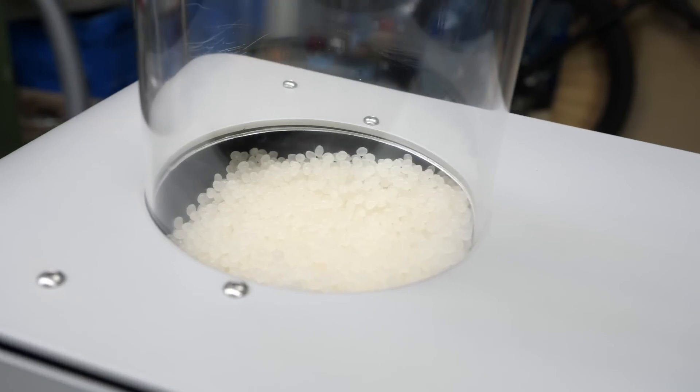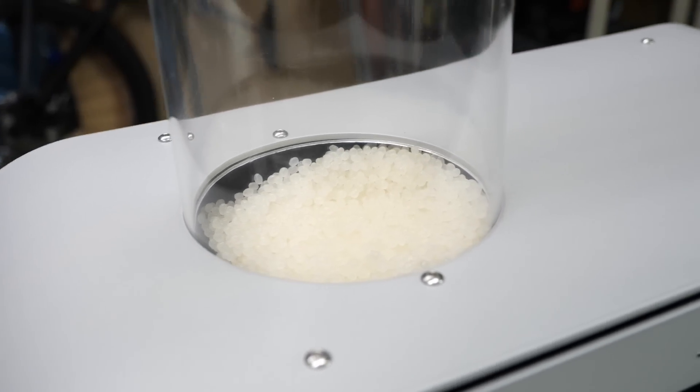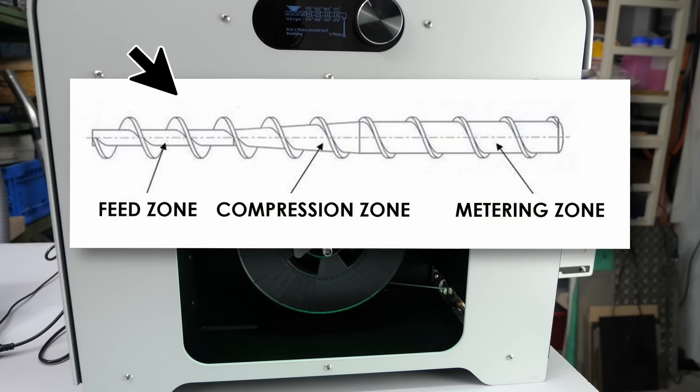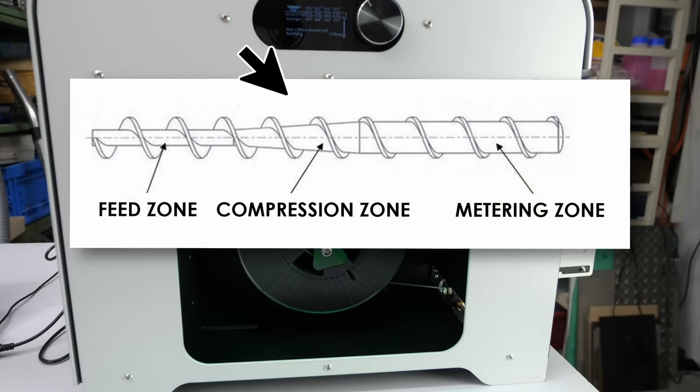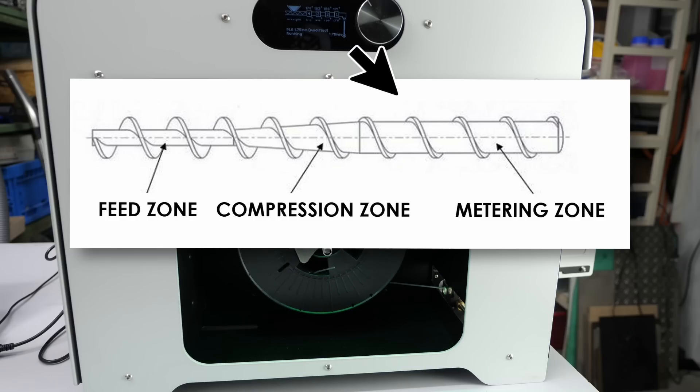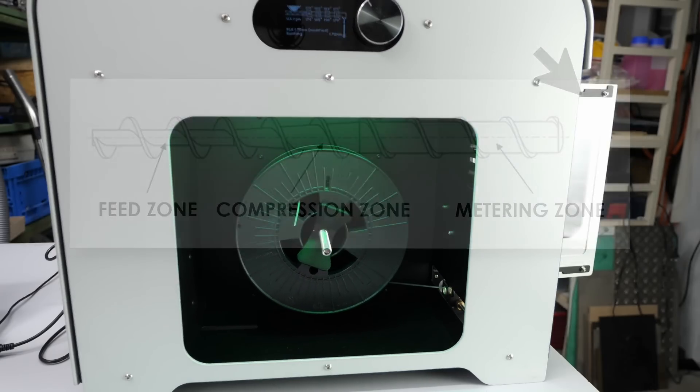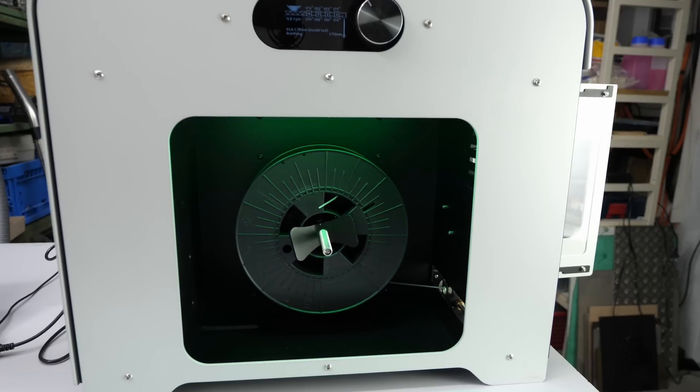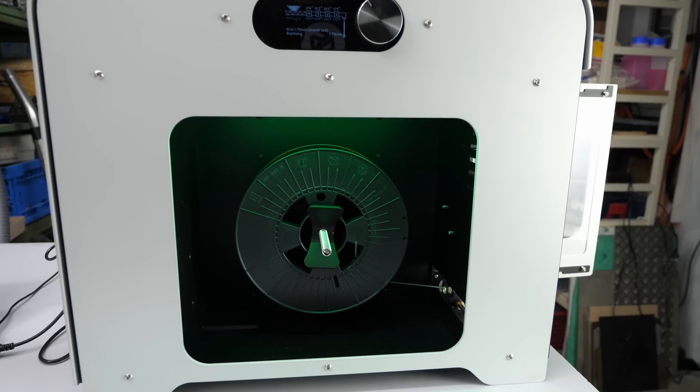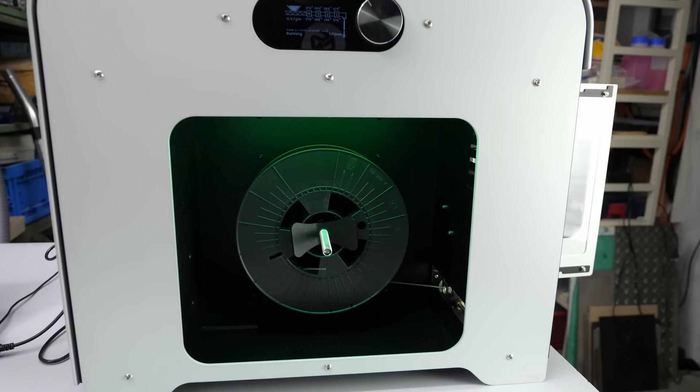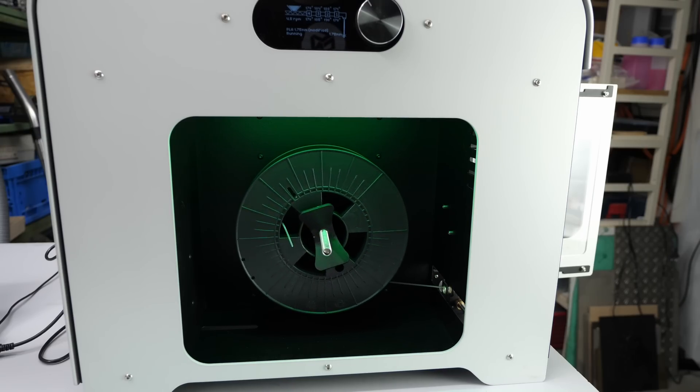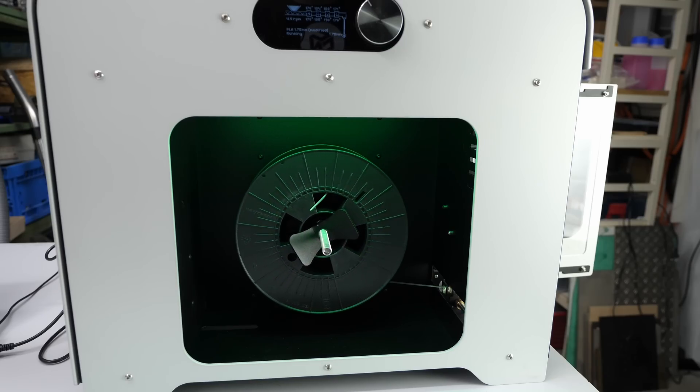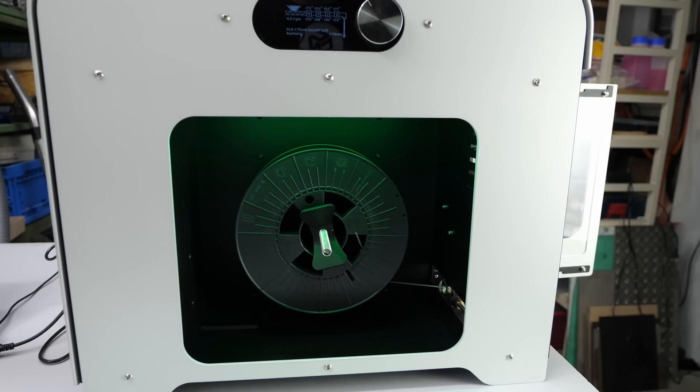The 3Devo Composer continuously adds new pellets through the hopper into the extruder where the 3-zone compression screw first feeds it, then compresses and starts to melt it and finally fully melts it and especially homogenizes it in the so-called metering zone before it leaves the nozzle. Just as an interesting side note, you might think that the material primarily melts due to the heaters around the barrel, but especially in the metering zone at the end, a significant amount of heat is internally generated just by the friction and the shear motion that the particles and also the melt does.